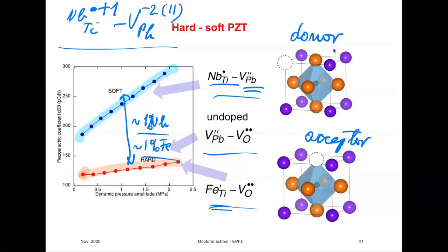Now, why does PZT prefer to have compensation with the lead vacancy rather than with the electron? Well, it turns out that it is very easy to get rid of lead in PZT. Lead will easily evaporate. Some lead vacancies are already present in the material when we start. Oxygen can be exchanged with the atmosphere, and we know, both empirically and from calculations and so on, that this is the equilibrium defect concentration in a PZT.